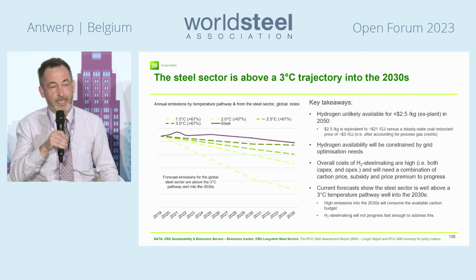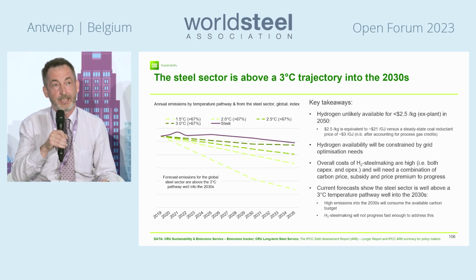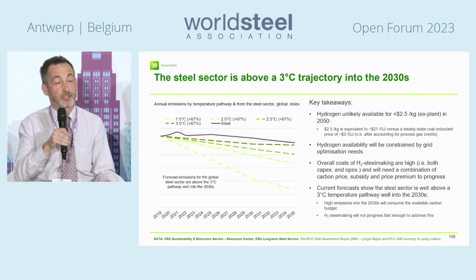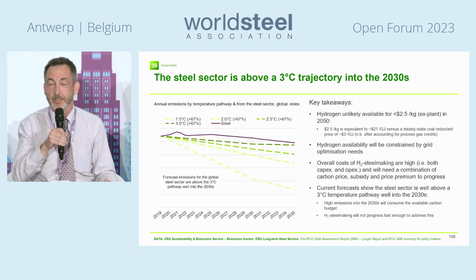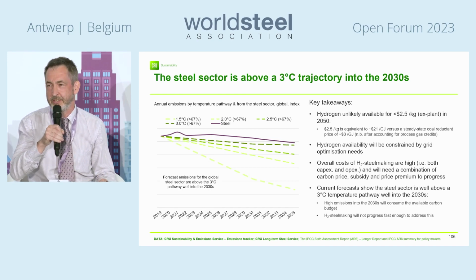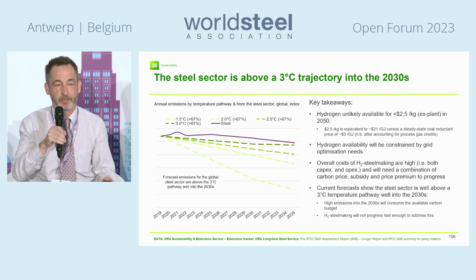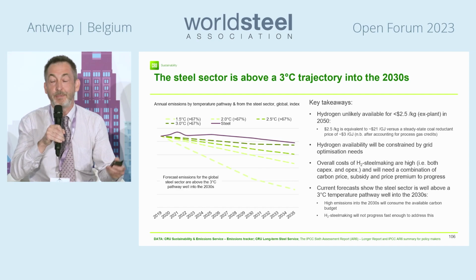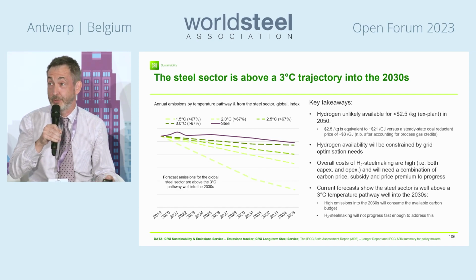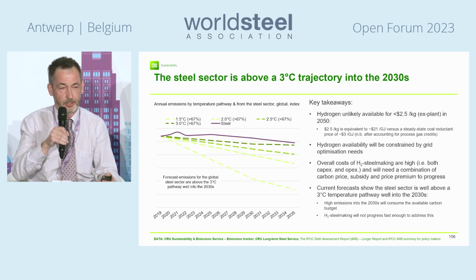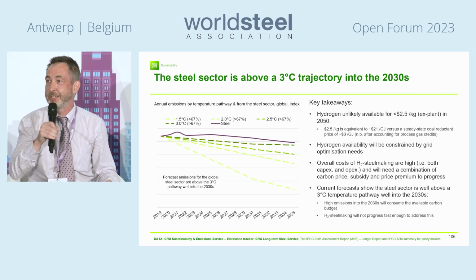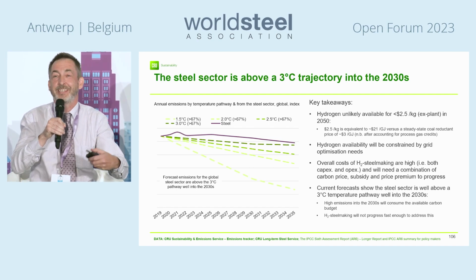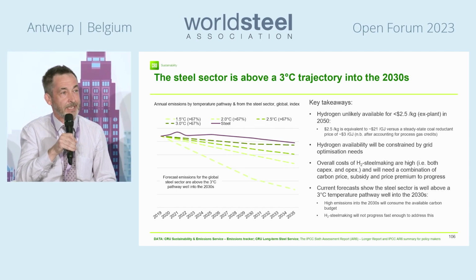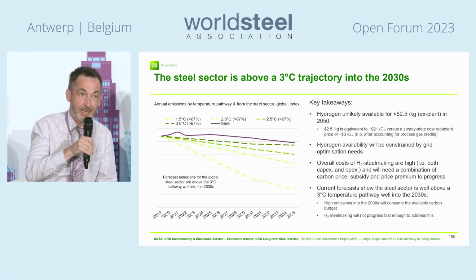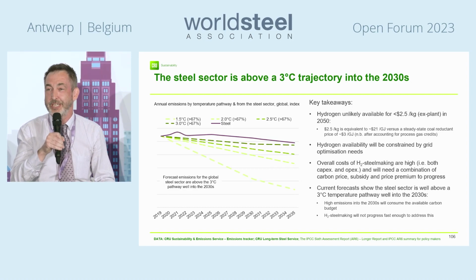This is my last slide. The left-hand chart shows our forecast for carbon emissions from the steel industry globally out to 2050. The dark line. The dashed lines are the IPCC temperature pathways, 1.5 degrees to 2.5 degrees, 3 degrees. We believe that the steel industry into the middle of the 2030s and a little bit beyond to 2035 is on a plus 3 degree pathway. That's where we are. This is taking into account all of the projects that have been announced. It's taking into account the extra scrap that is available. It's on a plus 3 degree pathway.